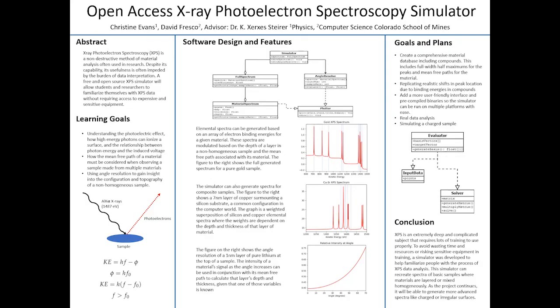Another thing it can do is it can do angle resolution, which is a process of tilting your sample to produce a different spectrum as the angle increases. If you have a top layer on your sample, then as the angle increases, the perceived thickness of that layer will increase and the signal from that particular layer's composition will get stronger.